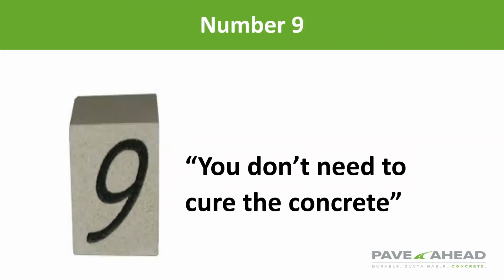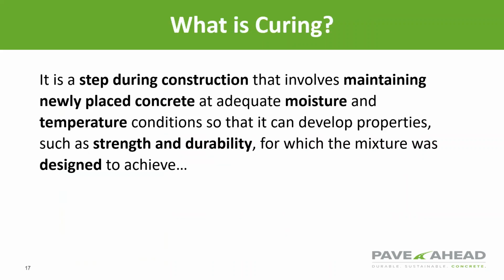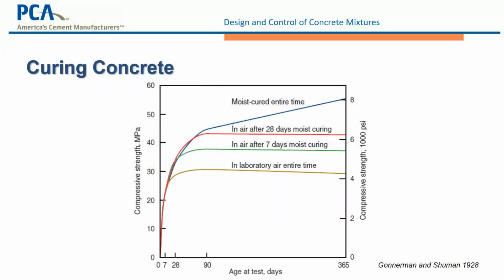Don't need to cure the concrete. Well, what is curing? It's a step during the construction process that involves maintaining adequate moisture and temperature so concrete can develop properties such as strength and the mix was designed to achieve. So with proper curing, concrete becomes strong. Strength that it was designed for, rapid at earlier ages, but continues thereafter for an indefinite period. And it shows if you don't cure the concrete, that is much lower.